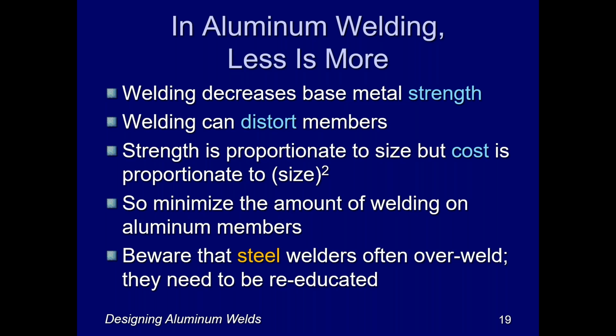Until a couple of years later, I got involved in aluminum welding, and then I realized there are times when less is more, and that is in welding aluminum. The less welding you do on aluminum, the better off you are. And that's for many reasons. First of all, no matter how perfect your welding process is and how good your welder is, welding decreases the base metal strength of virtually all aluminum alloys that have been tempered to get a little more strength. So it wipes that out.